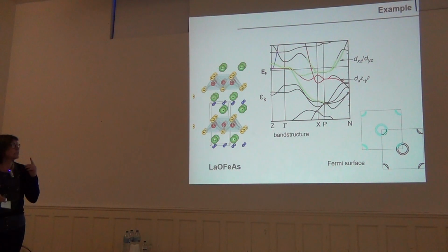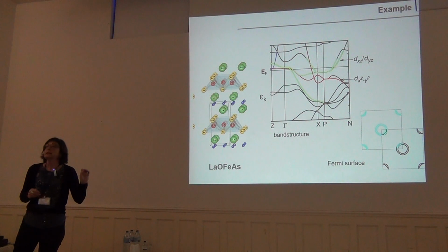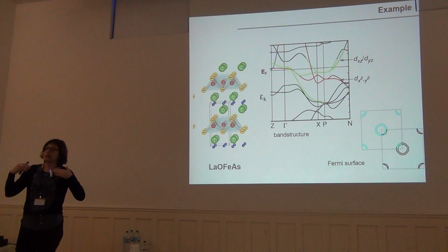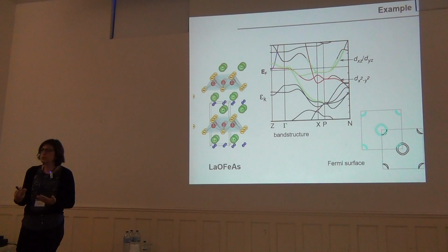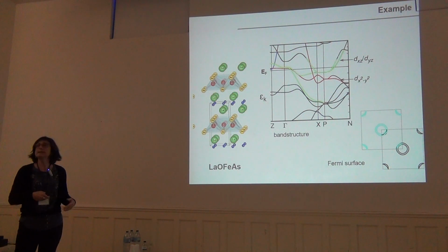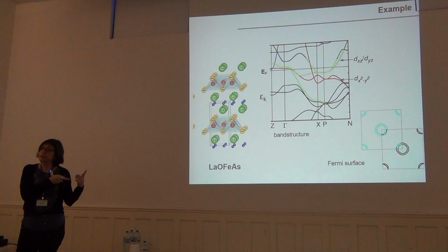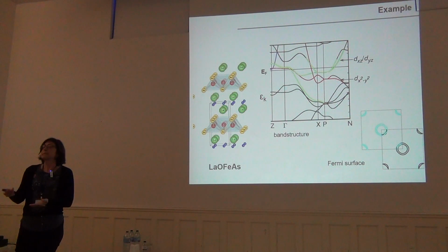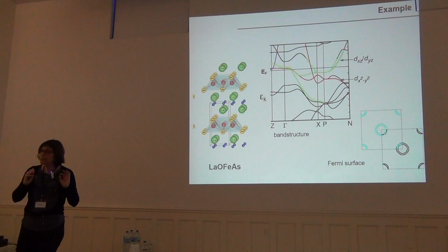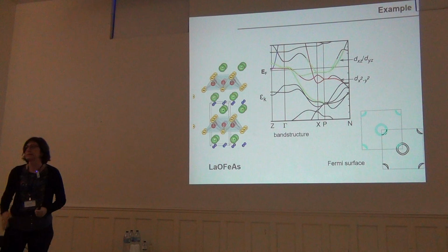How do we do that here for unconventional superconductors? For unconventional superconductors, we start from the assumption that the unconventional superconductivity is mostly driven by spin fluctuations. If we make this assumption, what we do is take the information from the DFT, derive effective models, and then treat them with methods to obtain superconducting properties. But from DFT directly, you cannot obtain unconventional superconductivity. Okay, it's for the normal state.